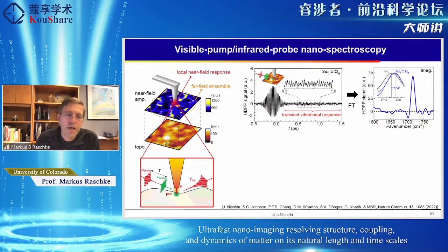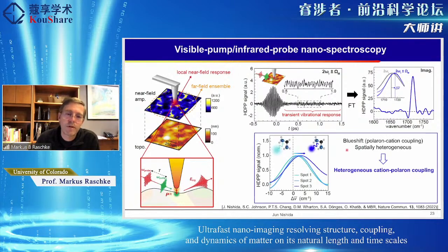So if you do it spectrally resolved in this transient vibrational response following the pump excitation, the Fourier transform of this gives you again this formamidinium cation response. And then if you compare that peak position with the ground state response, which we did the spectroscopy, which I showed you just earlier, then we see a blue shift. And so this blue shift is expected and is consistent with this physical picture that this polaron cation coupling gives rise to the spectral blue shift as a signature of this excited state vibration.